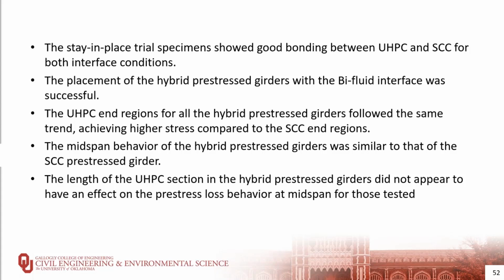The midspan behavior of the hybrid prestressed girders was similar to that of the SCC prestressed girders, and the length of the UHPC section in the hybrid prestressed girders, whether it was 3 or 5 feet, did not appear to have an effect on the prestress loss behavior at midspan for those tested.